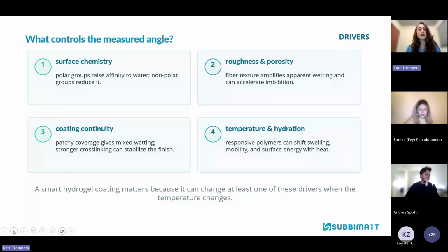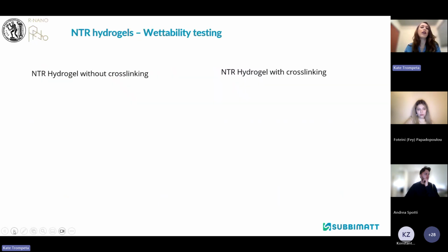Last but not least, we have the temperature and hydration, especially for smart textiles that would like to function with an openness for functionality. So here we have responsive polymers that can shift swelling. We also need to study the mobility of the chains and the surface energy based on the heat. A smart hydrogel coating matters because it can change at least one of these drivers when the temperature changes. So this means that we also need to measure the wettability because that is how we understand how this smart textile can function.